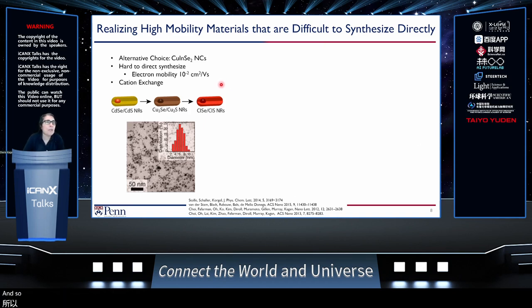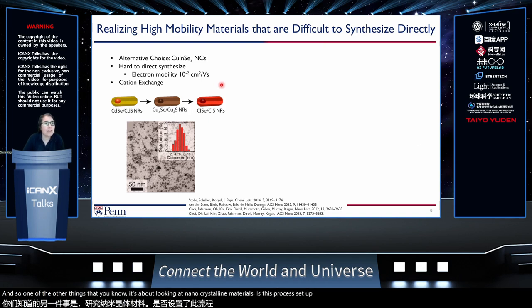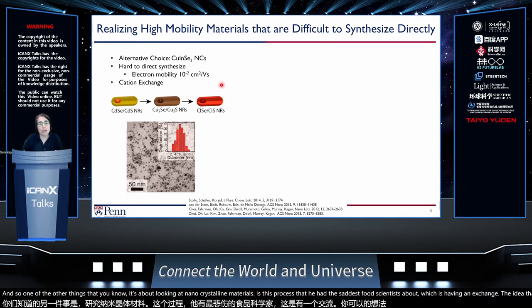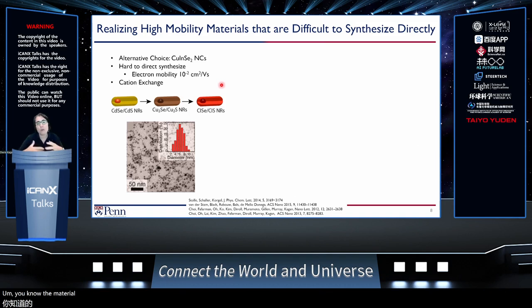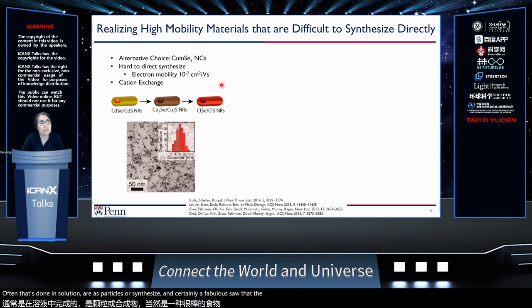And so one of the other things that's unique about nanocrystalline materials is this process that the Alivisatos group taught us about, which is cation exchange. The idea is that the materials are small, so you can replace one cation for another. Often that's done in solution as particles are synthesized, and certainly a fabulous tool that the community has used. One of the things we were interested in is, could we do that in the solid state and start with something that we know well?